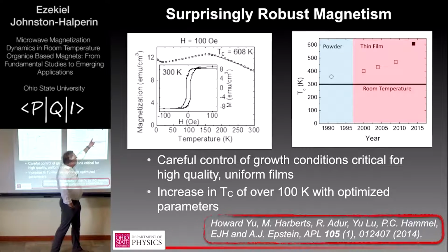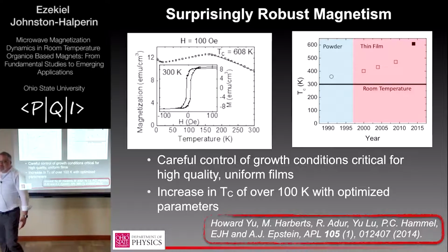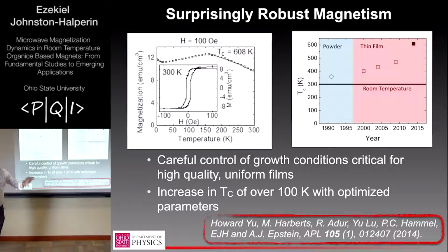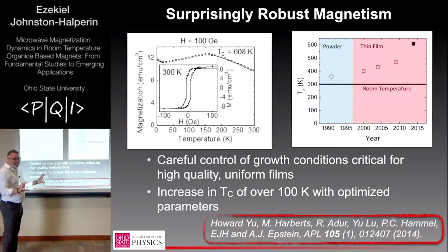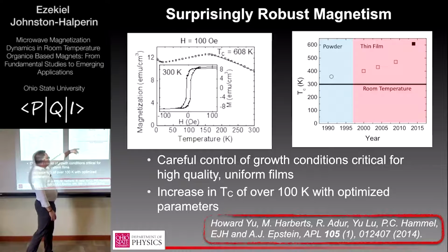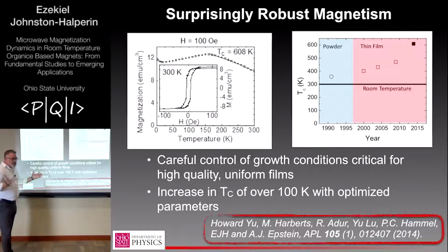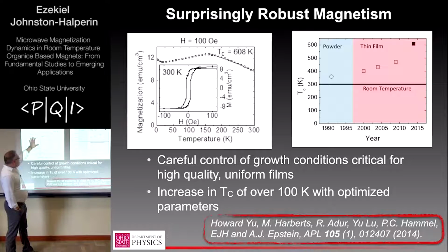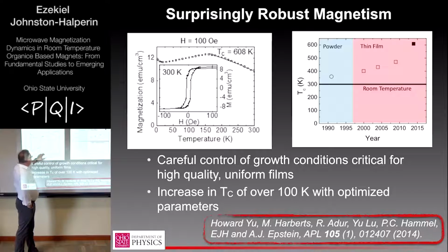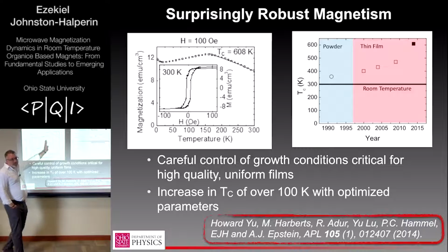And the reason why this curve looks the way it does is no dramatic insight. It's basically just slowly and carefully, systematically getting better control of the growth conditions and all the grunt work of material science that makes things go. And so this 600 Kelvin Curie temperature is more or less our current state of affairs for optimized material. There's some structure in M versus T, which I can talk about in a second. But if you just do a very crude analysis at room temperature, it's within 85% of its maximum magnetization.